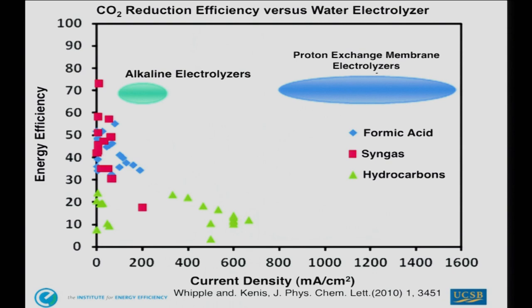And the issues here, and this comes from Whipple and his co-workers at the University of Illinois Urbana, who did a kind of data mining literature search summarizing the energy efficiency. The alkaline electrolyzers are for water splitting, and the energy efficiency for that is appropriate, about 70%. There was moderate energy efficiency for the CO2 conversion. And it's easy to make carbon monoxide and formic acid, but it gets to be a problem when you're making the hydrocarbons, and primarily because of overpotential problems with that.